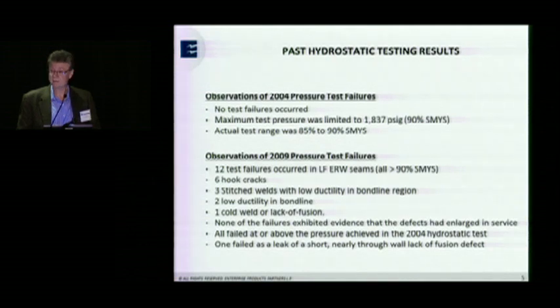Five years later, we pressure tested again in 2009. In this case, we took a little bit more aggressive look. We said, let's increase so that we get all the pipe segments above 90%. And we did have 12 test failures: 6 hook cracks, 3 stitch welds, 2 low ductility bond lines, and 1 cold weld or lack of fusion. Once again, we did not observe any fatigue or any fatigue growth on any of this pipe.